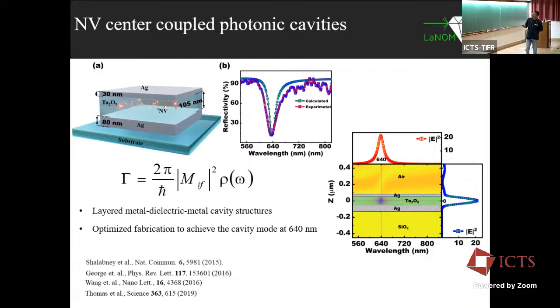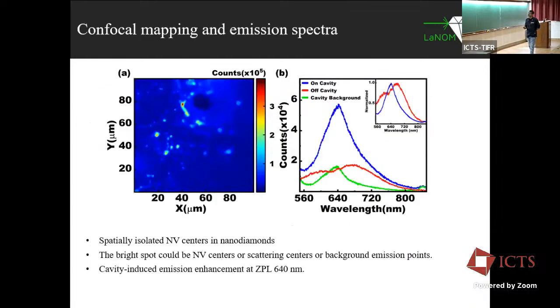And if you look at the field calculations by FDTD simulations, you can see that within the cavity layer the field is quite enhanced or localized. So that means if I place a dipole or an NV center here, I should be able to control the emission properties. And that's precisely what we did in the experiments. So we fabricated this sample with NV centers dispersed on the cavity layer, mounted it in our setup, and took a typical confocal map of 100 by 100 micron. We can see a lot of nice bright spots. All may not be NVs, some may be NVs. So we have to check very patiently which one is actually an NV and coupled.